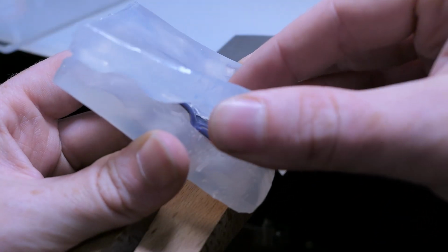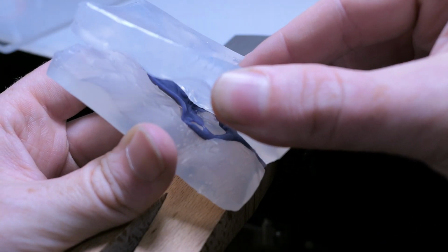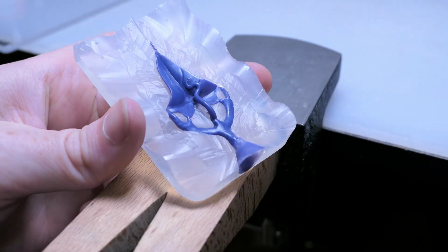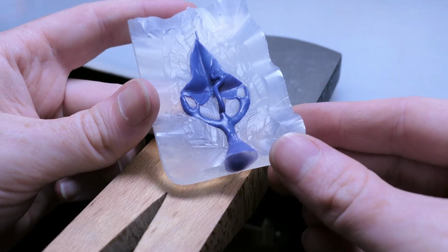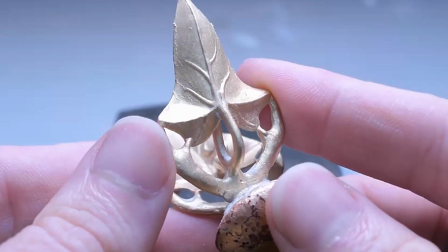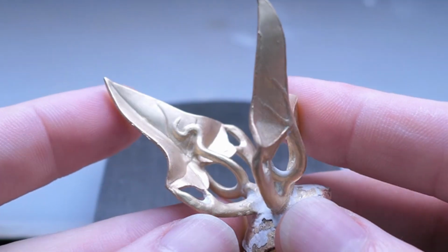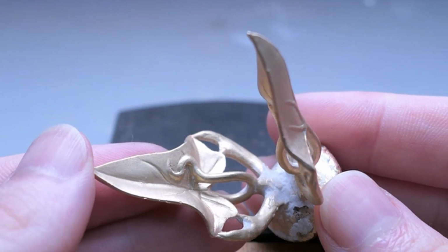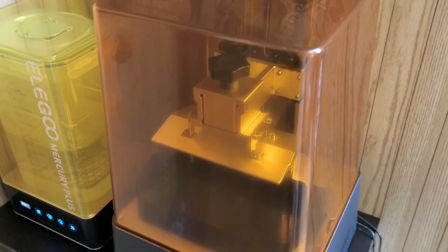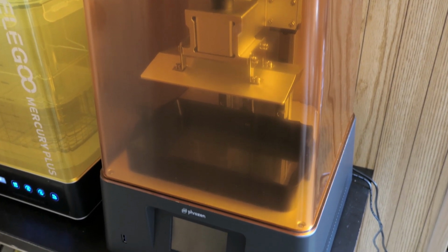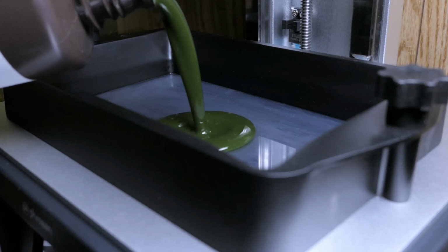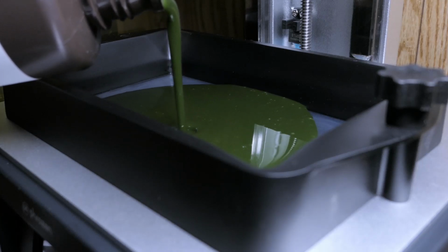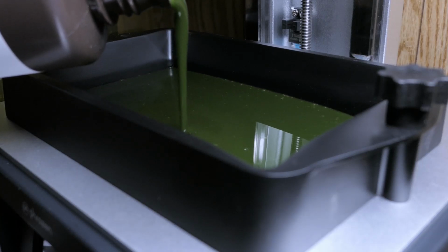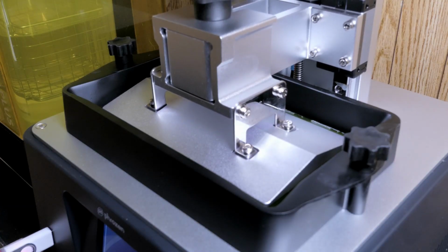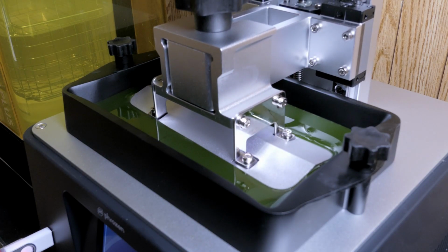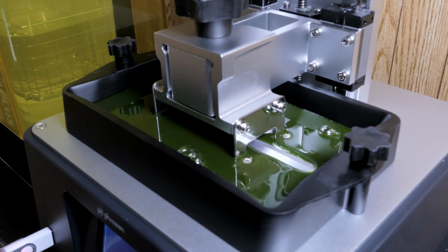So all that to say, there's just way too many variables that contribute to shrinkage to really be able to predict it. And it's something that makes metal casting really experimental with basically every new piece you're doing. But from what I've seen with doing some research and just experimenting with my own casting, it typically ranges around 1 to 5% of shrinkage, which doesn't really sound like a lot, but with jewelry making, that can make a huge difference if you're trying to be really precise.